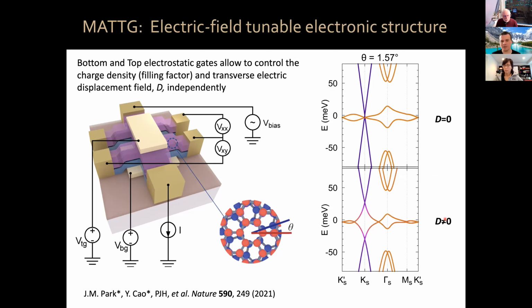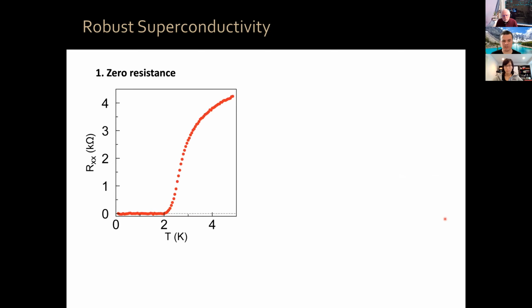All right. Let me show you first that the system is a robust superconductor. The first thing that you want to see is zero resistance. Indeed, if you measure the resistivity as a function of temperature, you have this big drop to zero. You can fit this with the Halperin-Nelson formula, and it gives you the BKT, Berezinskii-Kosterlitz-Thouless, transition temperature, which is 2.3 Kelvin for the system, and the TC at 50% of the normal state resistance is about 2.9 Kelvin.